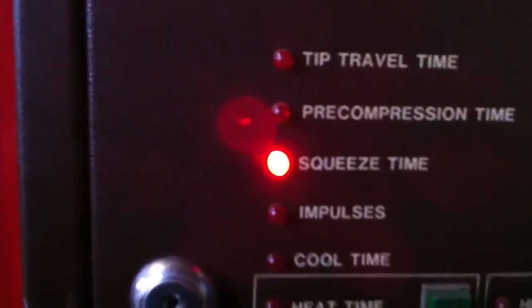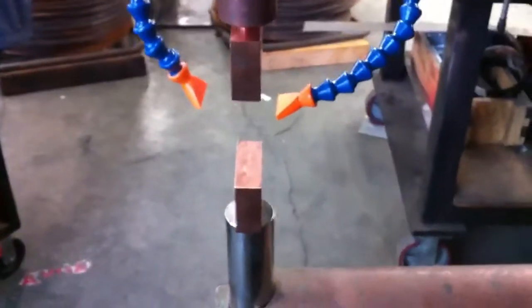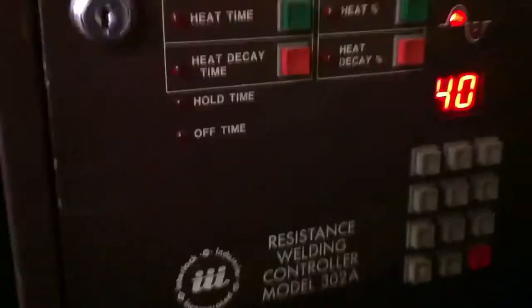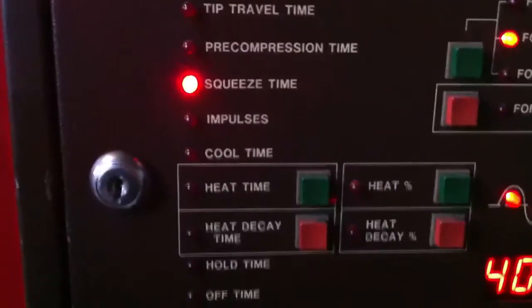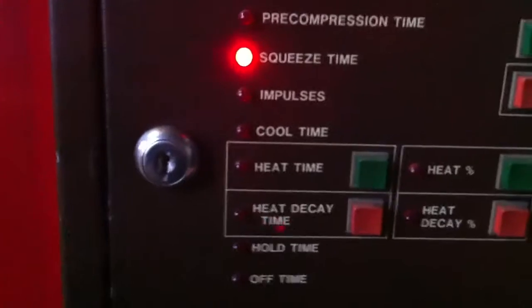So we scroll down with the red button, the squeeze time, and the amount of squeeze time is the amount of time it takes your tips to come together and build up pressure before it welds. If your squeeze time is too short, your tips will come down, your squeeze time will be over, you'll already be starting your weld time, and you'll come down hot and you'll blow holes in your part. So you always want to have enough squeeze time to come down and build up pressure before you fire.